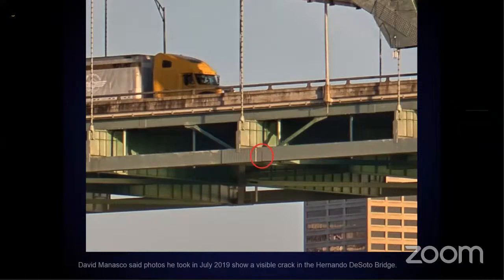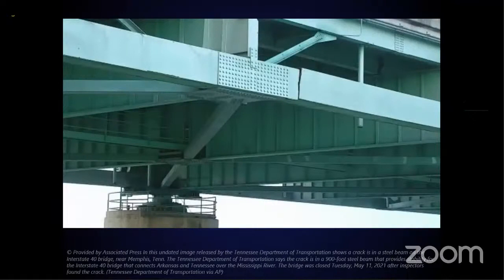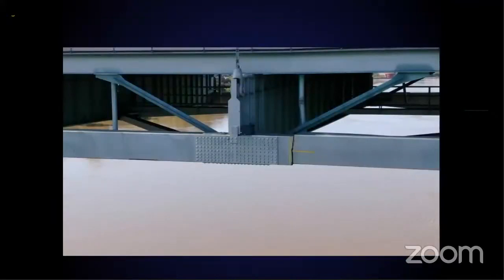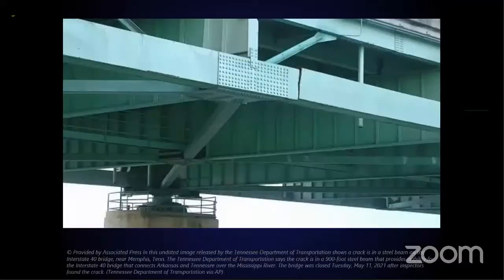The crack looked mostly like a fatigue crack due to thermal contraction and expansion, in addition to the dynamic load that comes from the vehicle traffic. You can see in that slide where I've marked the red circle, there is a crack. I'll show you some more. There is a crack over there, and you should note that fatigue is a failure mechanism that involves the cracking of the material in a structural component due to cyclic stresses.